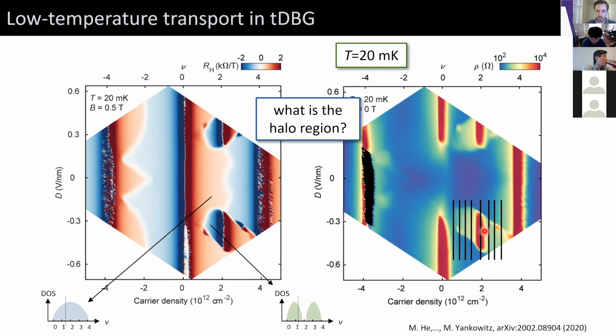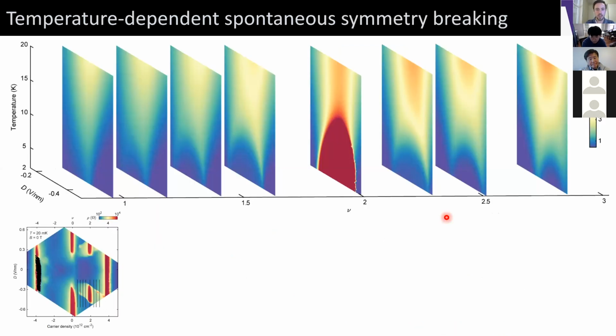So I'm going to show you the resistance at fixed carrier density as I sweep the displacement field for 8 different values of carrier density. And so those are these maps. Let's start with the one at half filling. What we see is basically this arch-like feature beneath which we have diverging resistivity. It's red, it's very high. And this one corresponds to the case where we're precisely at half filling, and the boundaries of this arch at low temperature are basically mapping out the boundaries of this correlated insulating state. I didn't mention, but this correlated insulating state seems to need that both the neutrality point and full filling are insulating so that the band is isolated.